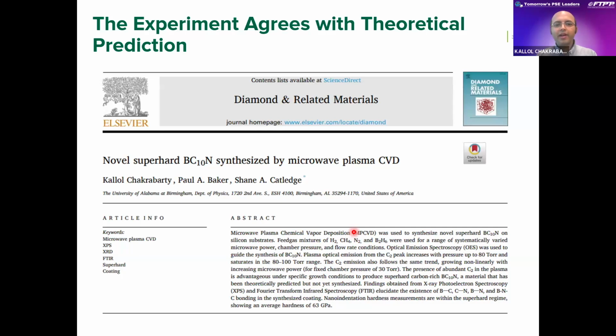So this is good agreement between the theory and the experiment, and we were able to publish this manuscript in Diamond and Related Materials. What Dr. Chen predicted theoretically for the BC10N material, we have synthesized and published as a paper in Diamond and Related Materials. So we can say the experiment agrees with the theoretical predictions.